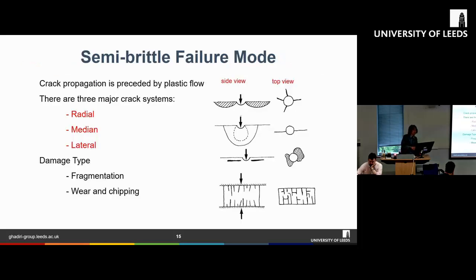Right, now let's move on to semi-brittle failure. So what's different? Semi-brittle failure is different from brittle material. The most obvious characteristic of semi-brittle material is that you can actually observe plastic deformation of the material before it actually fails. So here you can say that the crack propagation is actually preceded by plastic flow. So you experience some sort of plastic flow before a crack is initiated.